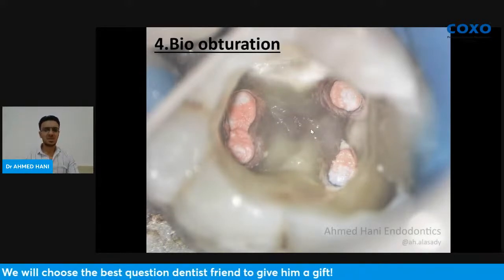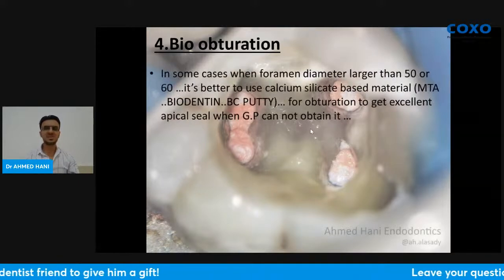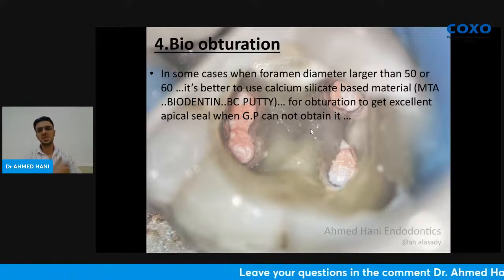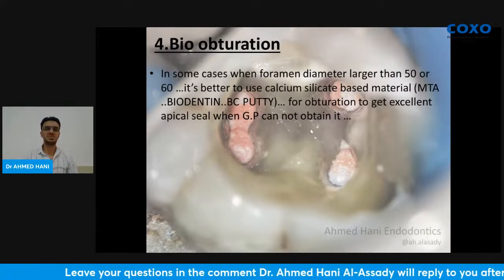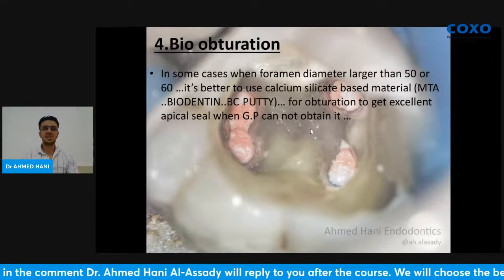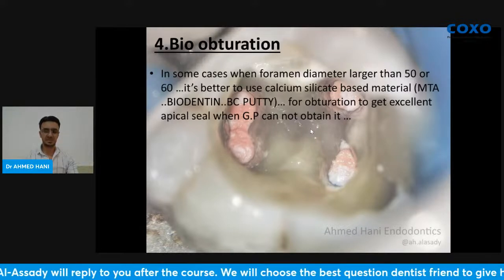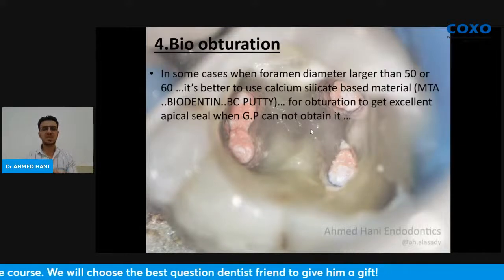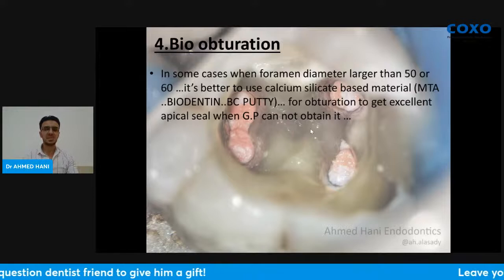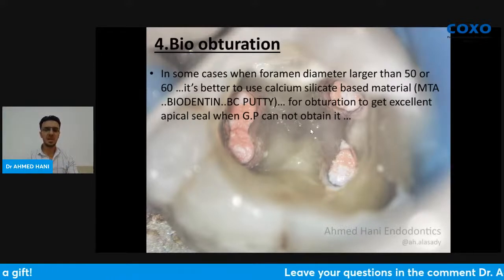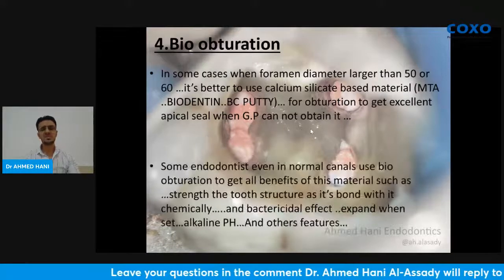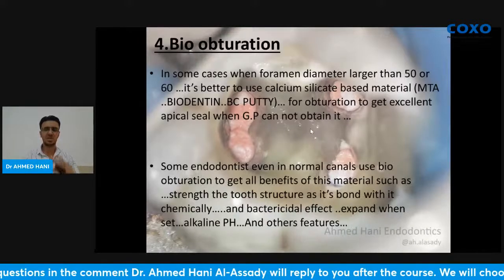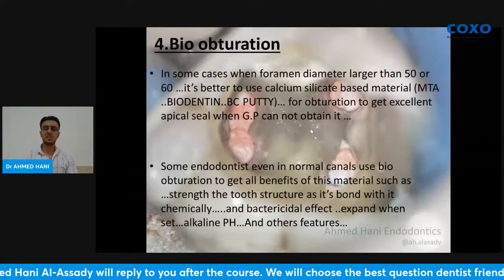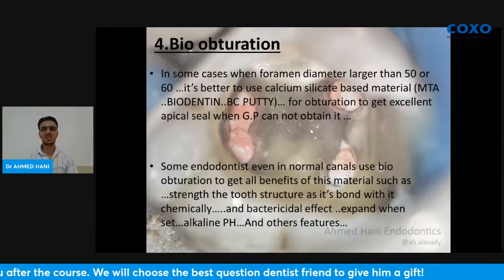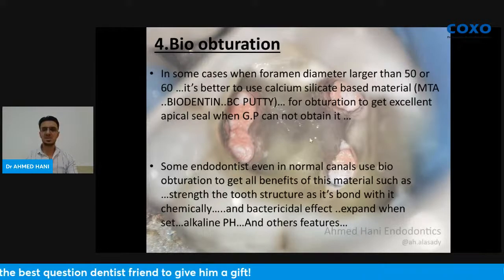Let's talk about the last one, which is bioobturation, which uses a calcium silicate base. In some cases, when the foramen diameter is larger than 50 or 60, it's better to use a calcium silicate based material, MTA, Biodentine, BC Putty, for obturation to get excellent apical seal when gutta-percha cannot obtain it because of the large diameter of the foramen. With gutta-percha I cannot get a real and perfect apical seal, so I go for bioobturation by calcium silicate based materials. Some endodontists, even in normal cases, use bioobturation to get all the benefits of this material, such as strength to the structure, its chemical bond with it, bactericidal effect, expansion when set, alkaline pH, and other features of these materials.